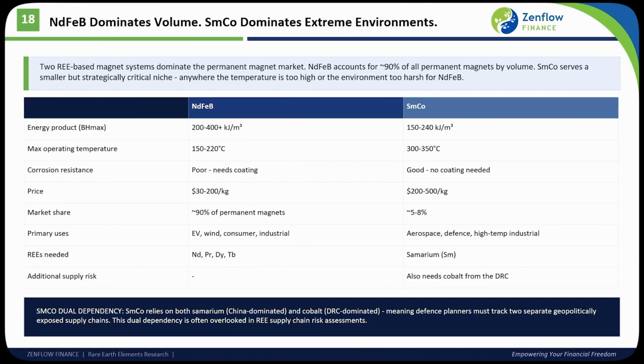The rare earth permanent magnet market is dominated by two systems, NdFeB and SmCo, which is samarium cobalt. Let's understand how they differ and why both matter. NdFeB accounts for approximately 90% of all permanent magnets by volume. Its energy product is 200 to 400 plus kilojoules per cubic meter. It operates at a maximum temperature of 150 to 220 degrees Celsius. Its corrosion resistance is poor. It needs a protective coating. Price ranges from $30 to $200 per kilogram. It is used in EVs, wind, consumer electronics, and industrial applications. The rare earths it needs are Nd, Pr, Dy, and Tb.